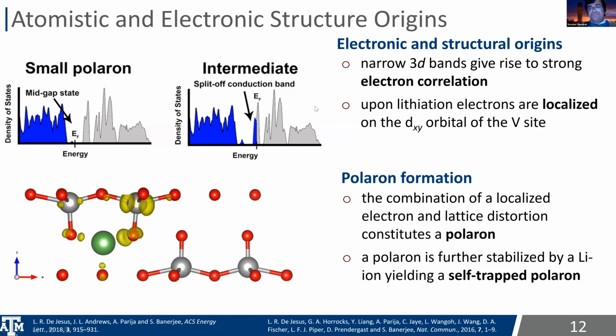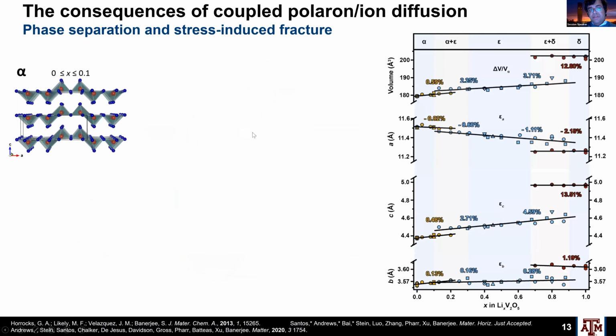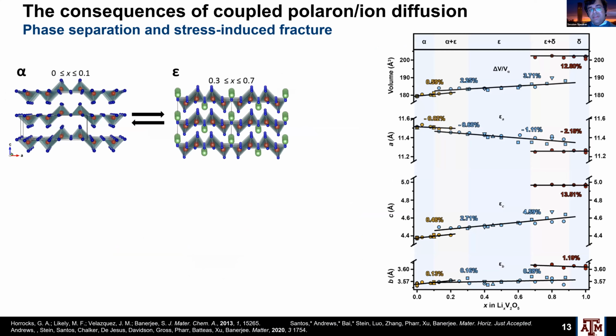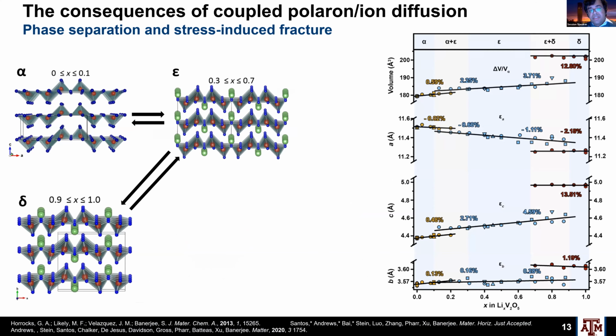Okay, and again, where this is coming from is this dxy being a split-off conduction band because of the square pyramidal nature of coordination of vanadium in V2O5, which then gives this very narrow band. Okay, and so as you get lithiated, because of the unfavorability of the square pyramidal oxidation state, the V2O5 structure actually tends to start becoming more octahedral, and the whole series of phase transformations.